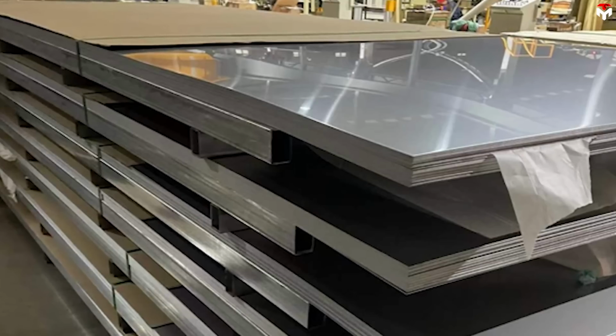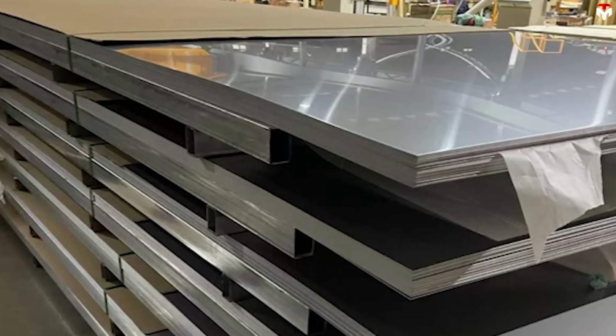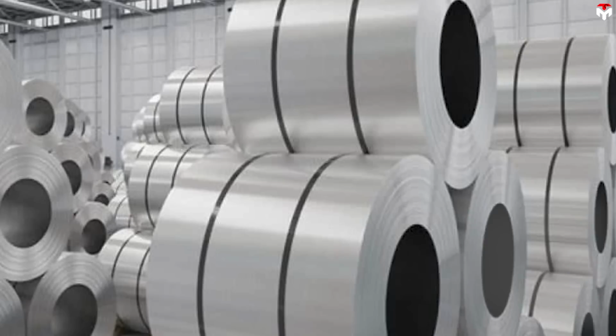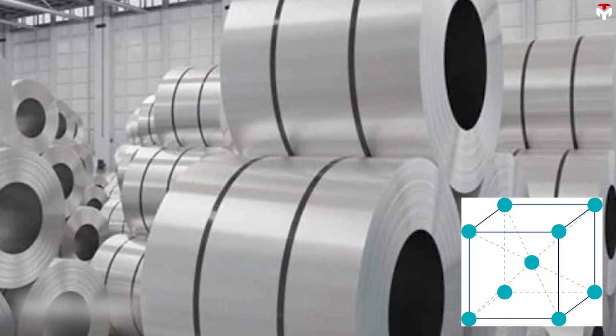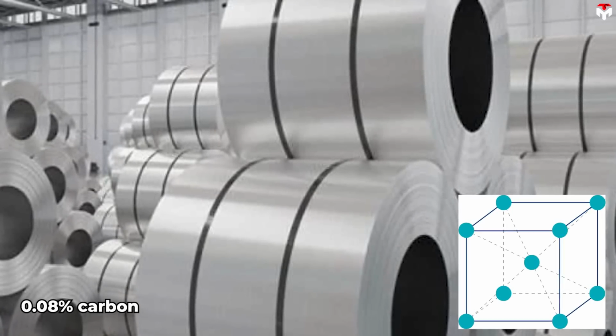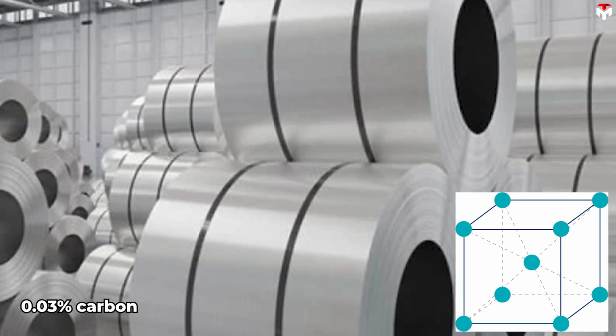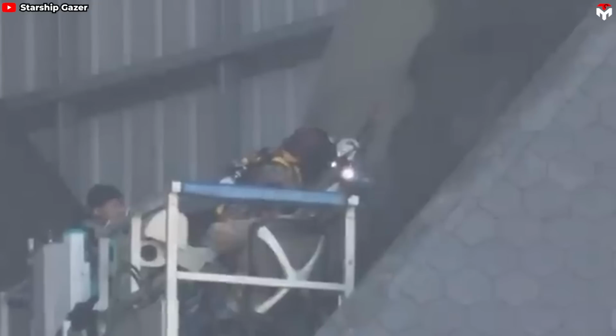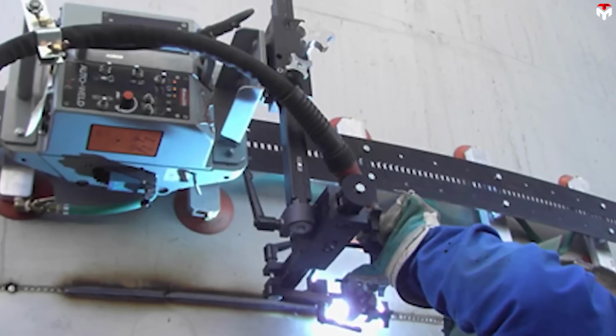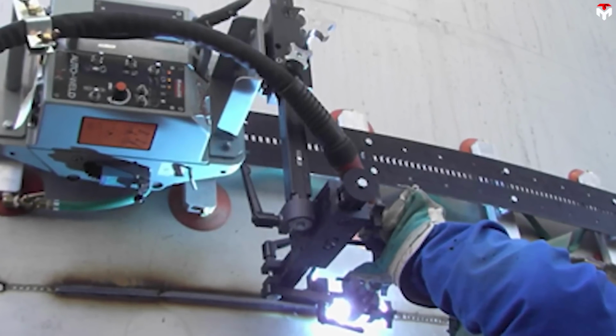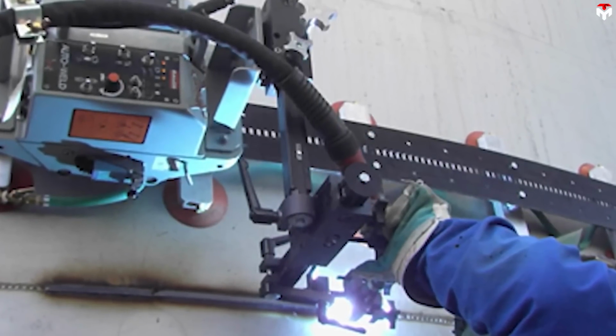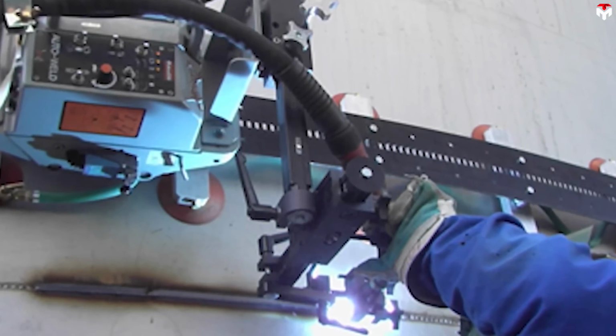and pots. The L in 304L stainless steel stands for even lower carbon content, while regular 304 can have up to 0.08% carbon. 304L can have up to 0.03%. Remember, Starship is made of welded steel rings, so the weakest point will always be the welds. While 301 welds are slightly stronger at higher temperature, at cryogenic temperatures, the strength of 304 welds is 4 times stronger. This switch should allow SpaceX to keep the welds of Starship as they are when finished, without any complicated, expensive, or even impossible aftertreatment.